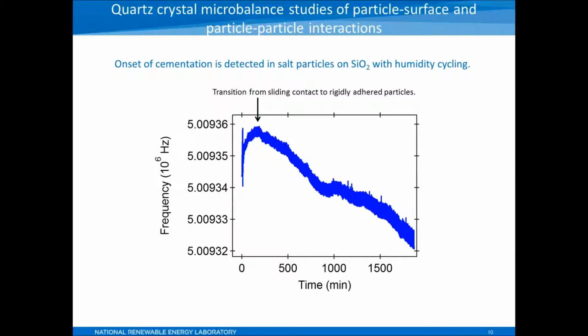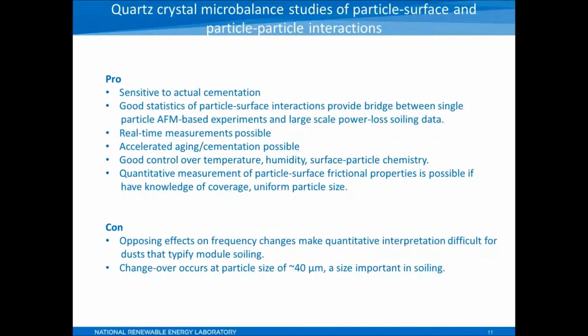Anyways, we can do this with other particles other than glass spheres. That's not really the problem with soiling, but we can detect the onset of cementation, and in this case we show an opposite trend. We have a decrease of the frequency. This means we've essentially been able to detect the transition from sliding contact to rigidly adhered particles. Since these are going to be available online, I can just let you quickly look at the pros and cons of this type of experiment.